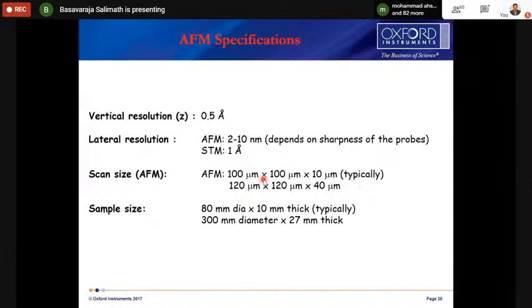Scan size depends on the scanners they are using, but typically it will be 100 micron by 100 micron by 10 micron height. And for the sample size, typically we can keep glass slides, and up to 10 mm thick samples. But based on the different models, we can keep big wafers, 300 mm wafers, with up to 27 mm thick samples.